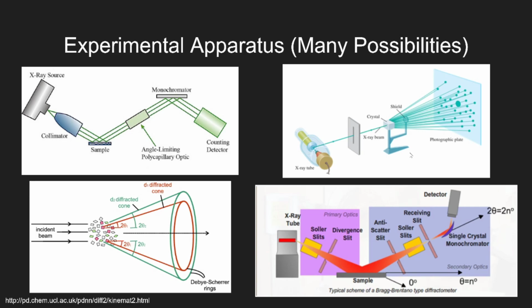And then finally, there are extinction effects. This is a problem regardless of powder or single crystal. If you have multiple reflections that are all associated with one lattice plane reflection, and you have a reflection which penetrates into a crystal, only 2 or 3 layers deep, and then it starts to come up, and it's perfectly oriented in a way where it bounces back again, some of it will go through the crystal, and some of it will reflect back. You end up with a cascading effect where some of them will be transmitted, but some of them won't. So the intensities that you might see may be lower and lower given this extinction phenomenon.